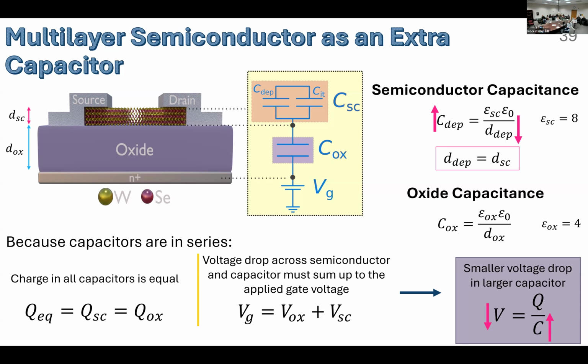So again, if we look at the capacitance value for a parallel plate capacitor, it is proportional to its dielectric constant and inversely proportional to its thickness. So for thinner flakes, meaning this thickness is very small, you have a higher depletion capacitance. If you recall, for any given parallel plate capacitor configuration, if you have a larger capacitance, the potential drop across it will be small, right?